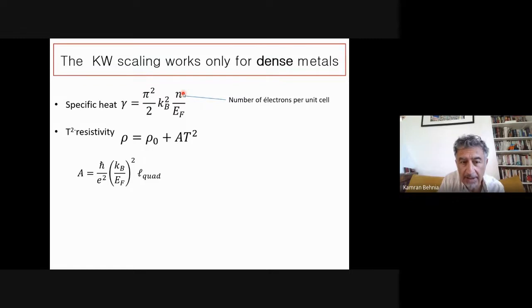If I now write the A term, this is a resistivity. This is the inverse of the quantum of conductance, if you wish. You have this term which represents the size of the phase space, and then in 3 dimensions, you will have a kind of phenomenological length scale that I will call L quad. Now, if n is equal to 1, then you would expect these two to scale with each other because the Fermi energy is the energy scale in both.